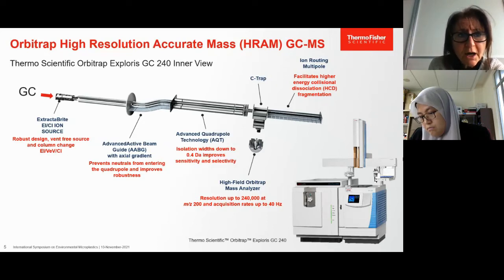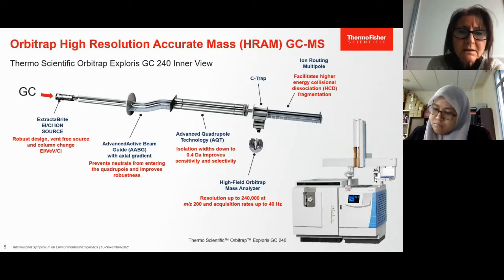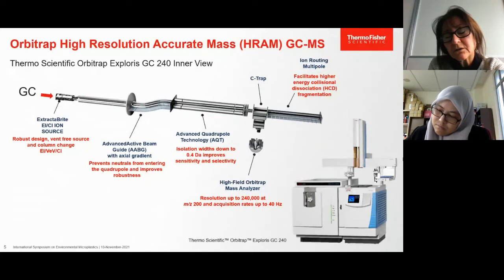Then there is an S-shaped ion guide preventing neutrals from entering the quadrupole, and this is reducing the noise and is also increasing the robustness of the system. The ions can then enter the AQT quadrupole, which is responsible for mass isolation for the selected ion monitoring acquisition or for MS-MS acquisitions. It allows for mass isolation down to 0.4 Dalton for improved selectivity, but at the same time, it is ensuring high ion transmission for high sensitivity.